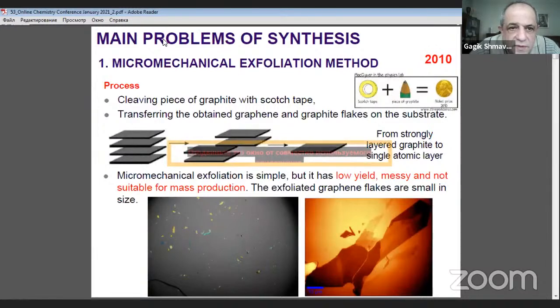So as you know, the first method is the micromechanical exfoliation method, which allows to get graphene flakes, but the micromechanical exfoliation is simple, but it has low yield, messy, and not suitable for mass production. The exfoliated graphene flakes are small in size. And the second method is CVD growth. This epitaxial growth is a high temperature process, and it is difficult to control the morphology and absorption energy. And the grown sheets have grain boundaries.